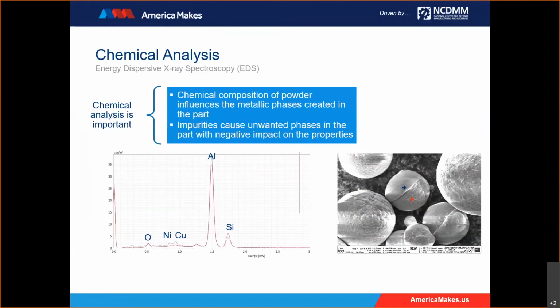So to identify the chemical variation in the powder lot, you should check your powder using SEM with EDS. Now, EDS can't quantify interstitial oxygen and nitrogen or carbon pickup. But in most cases, we know the desired composition of the powder batch, and we can easily identify segregation, precipitation, or contaminants that may lead to inclusions in the final part and have a direct effect on the mechanical properties.